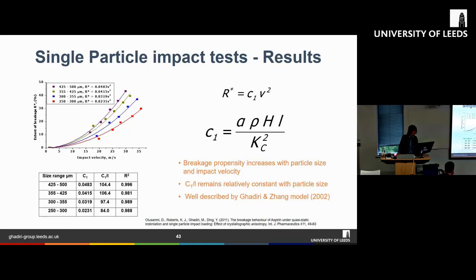Here, the four different series represent different particle sizes. The red line represents the smallest sieve cut of 250 to 300 microns, and the purple line represents the 425 to 500 micron particles. This type of analysis is done on a gravimetric basis. Essentially, we do that by sieving, something that Professor Tatsumi Matsuyama mentioned yesterday. So we do sieving, and these sizes are the standard sieve cuts that we use. We separate the particles into different sieve cuts, subject them to different impact velocities, and look at the extent of breakage. This is what we get.